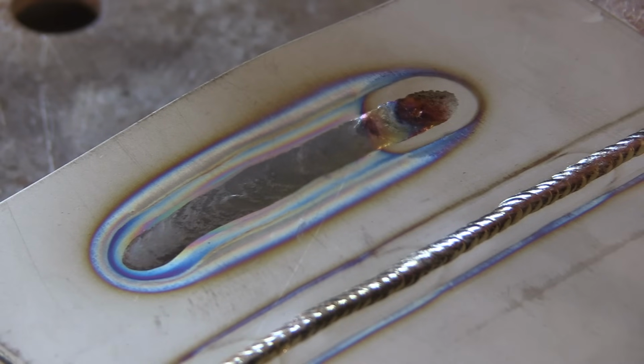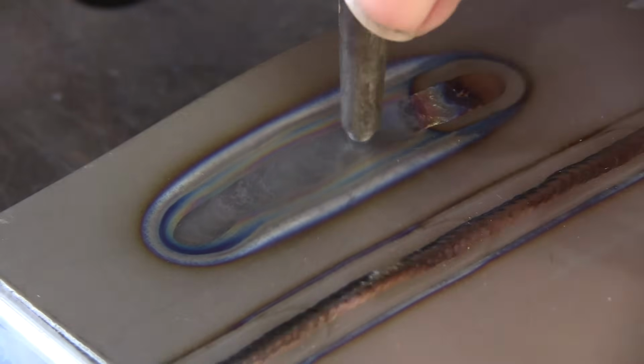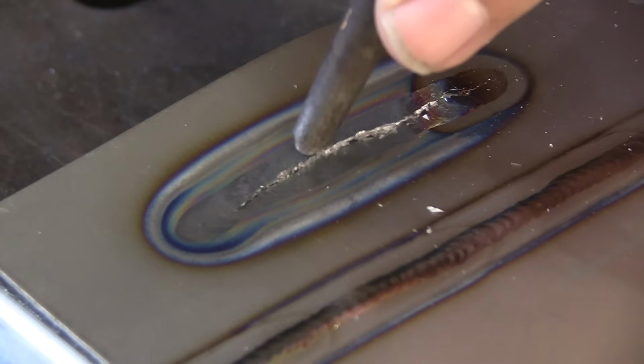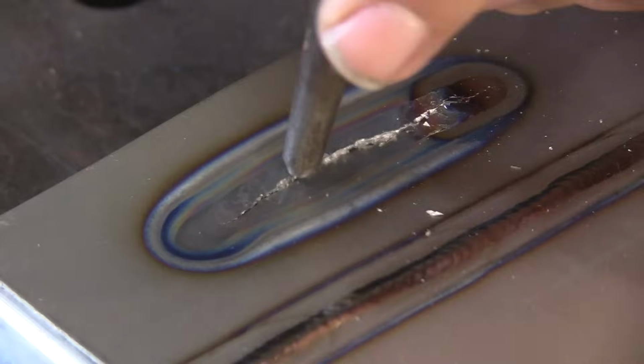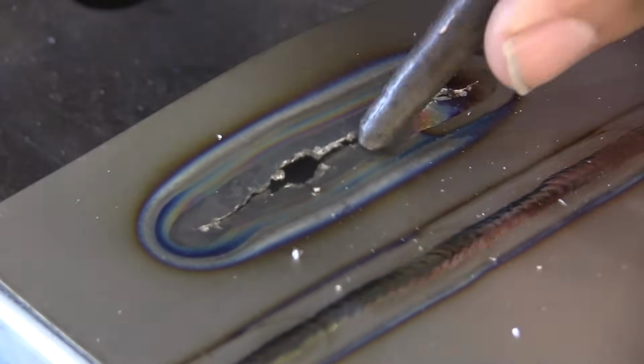It was the biggest mistake that you can make when welding titanium. There's a lot of talk about cleaning and argon shielding, but the worst thing you can do is weld it with the wrong rod. In other words, if you don't know it's titanium or you don't recognize it's titanium, it will turn into glass.